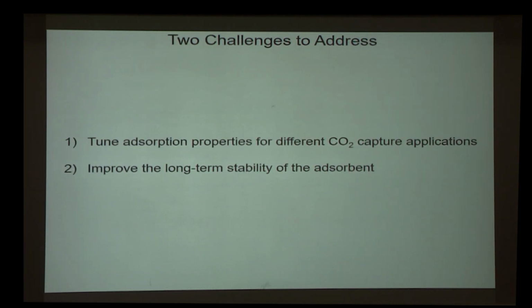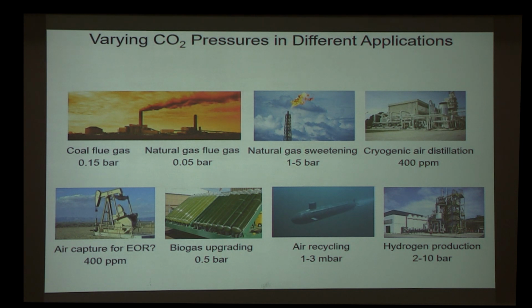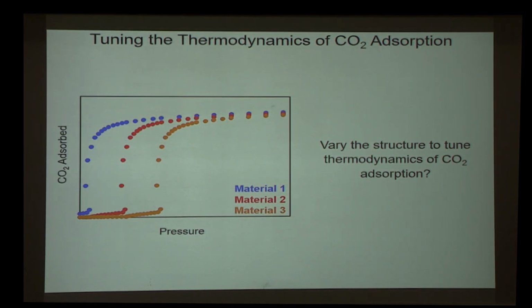At the time when I joined this project, there were two main challenges we needed to address. The first is we needed to tune the adsorption properties to make it usable for different CO2 capture applications. And the second is that we needed to improve the long-term stability of these materials. The motivation for tuning the adsorption properties is that there are many real-world CO2 capture applications, and the partial pressure of CO2 in the relevant gas streams can vary widely. It can be very high pressures, ranging all the way to very dilute pressures. And what you could envision is if we could change something about the structure of our material to tune the thermodynamics of CO2 capture, we would expect that the position of this CO2 adsorption step could be moved.